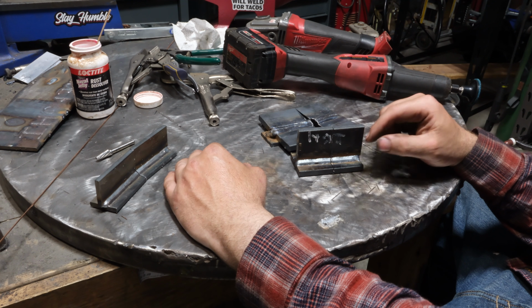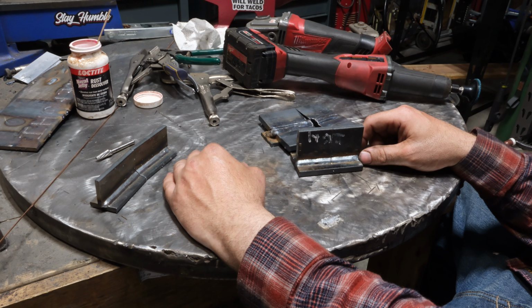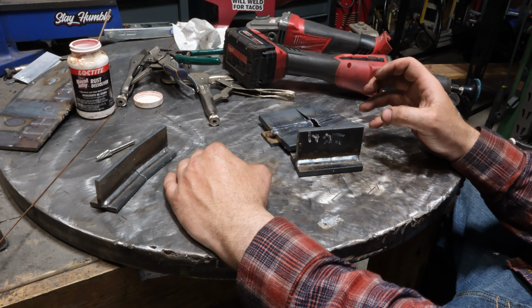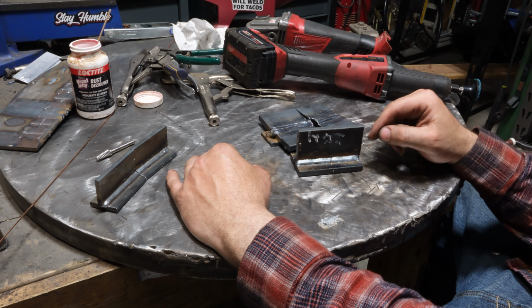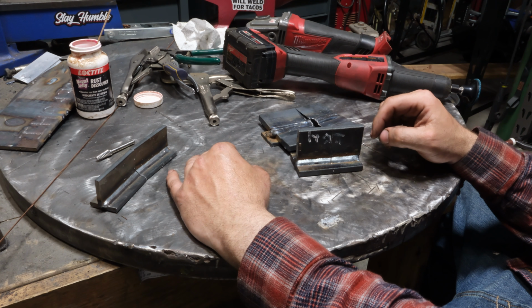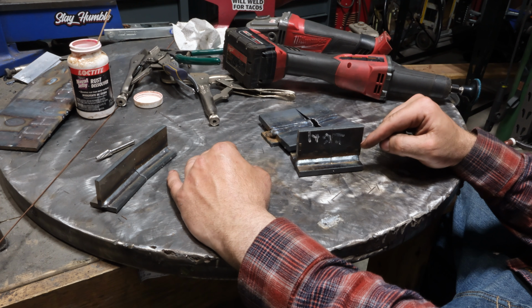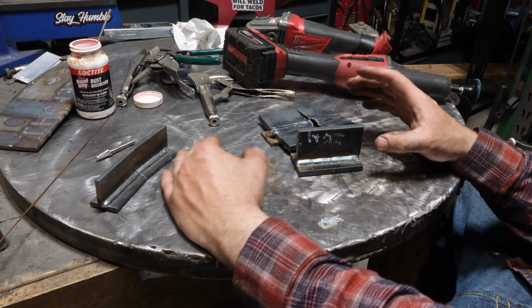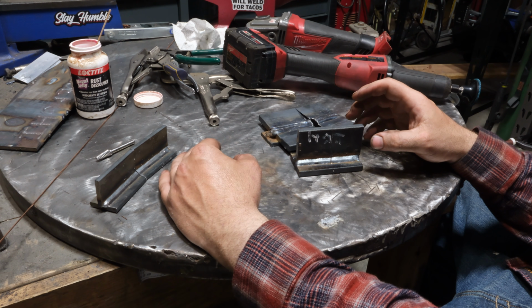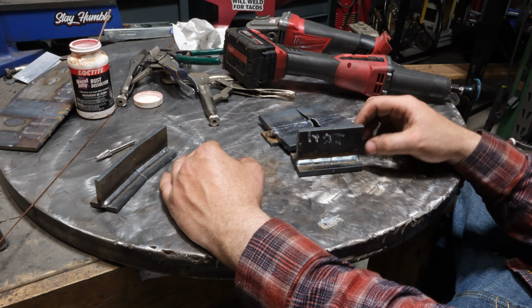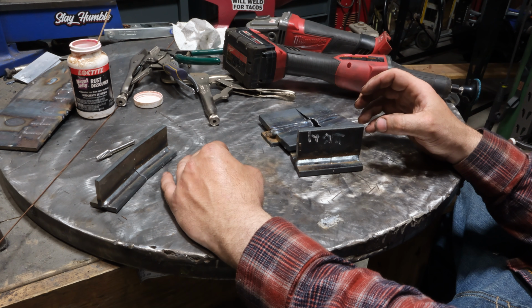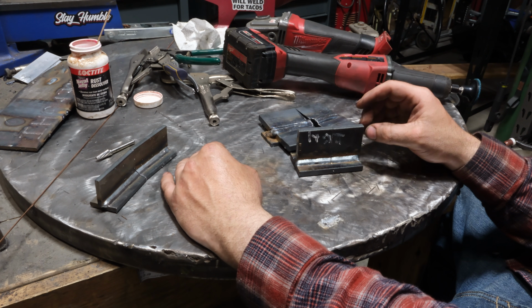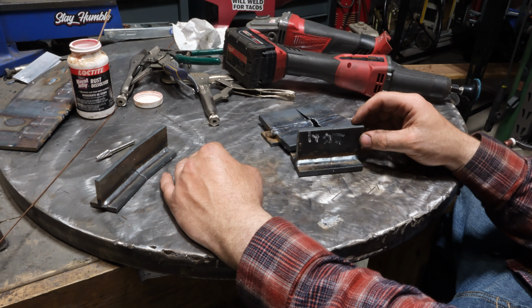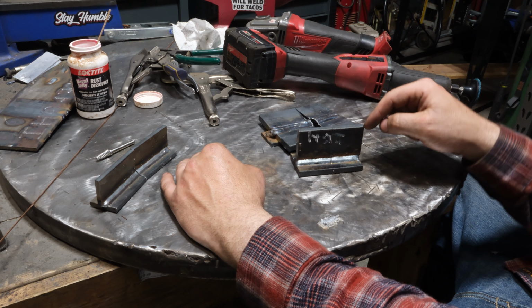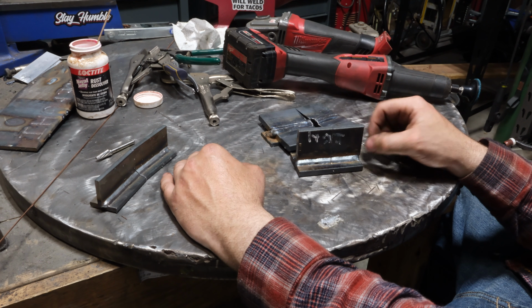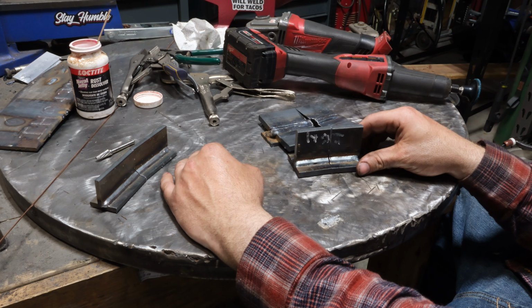Is your machine capable? Probably not, unless you have enough power to be getting up to these values that I ran the second one at. The other thing you guys got to consider with this, and like I mentioned earlier, I did a drag angle on all of these for the sole purpose of attempting to get as much penetration as possible. If you were to push this, I guarantee you your penetration would be worse and way more suspect. Not to mention the technique that I weld, where I go straight in and just do a smooth drag angle. A lot of guys out there like to do this circle ease and start spreading the heat over a large area. And I'm telling you, do a cut and etch on stuff like that on thick plate. You're going to see that manipulating it wider, often you get better sidewall fusion, but your depth of penetration in the root is worse. So that's something to be highly suspect of.